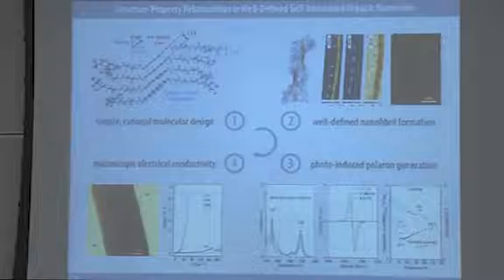And at the same time, the core molecules interact very strongly. And as a result, we see for the first time the photo-induced generation of surprisingly long-lived polaron-like charge carriers in the absence of a dopant. And we can show that these charge carriers are actually responsible for the macroscopic conductivity that these nanofibrils show. So this is kind of the outline of the story I would like to present to you today.